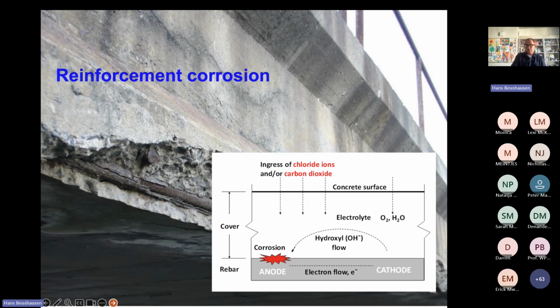And the one is the ingress of chloride ions, which is important for example in Cape Town and Durban, or any city or any structure located along the coast, because we have chlorides, salts, in the ocean, and if they enter the concrete, we can get reinforcement corrosion, because in that case, that protective layer on the steel is destroyed. And similarly, if you get the ingress of carbon dioxide, where we talk about carbonation, and then together with the carbon dioxide, we have water entering the structure, the concrete carbonates, which lowers the alkalinity. And remember, the alkalinity is the factor that gives us the protection. And once the carbonation front or the chloride front has reached the steel, then steel reinforcement corrosion can be initiated.